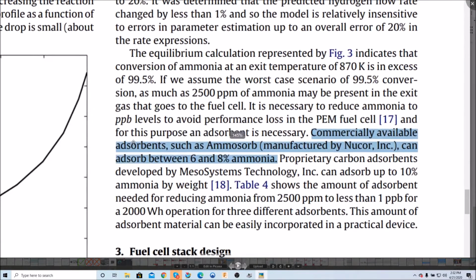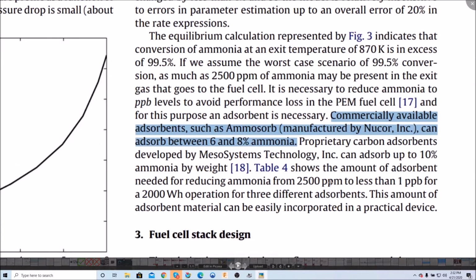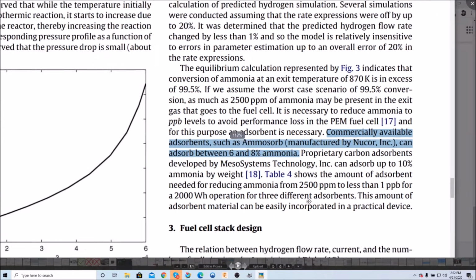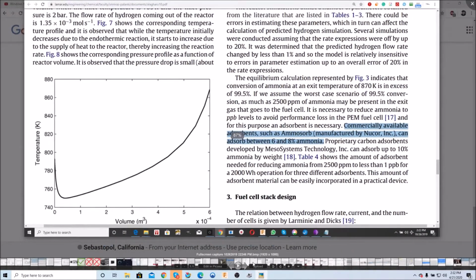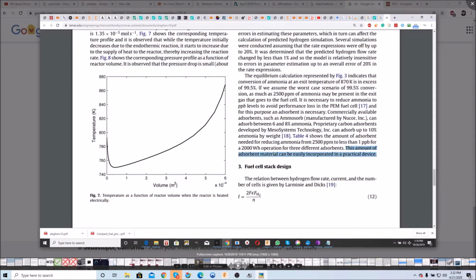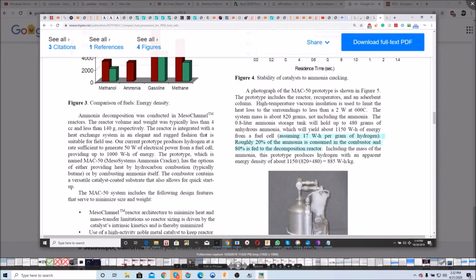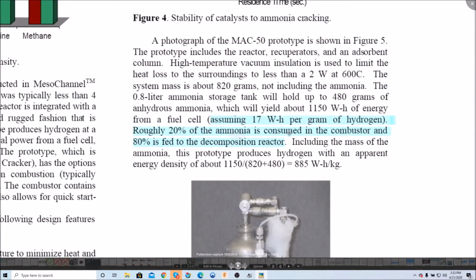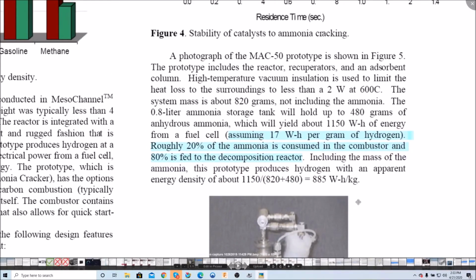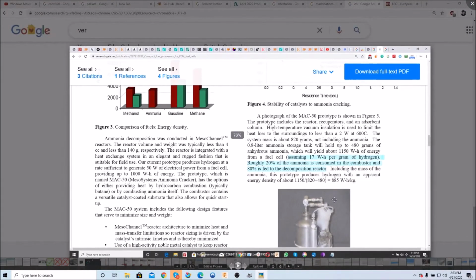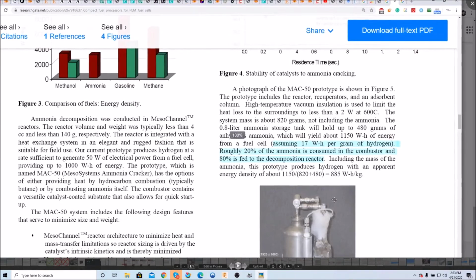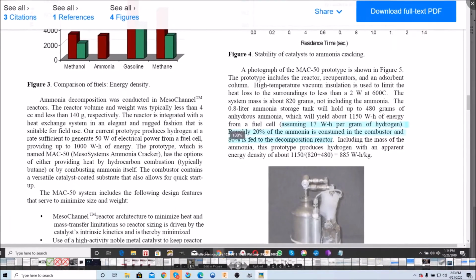So Ammosorb, between 6 and 8% ammonia by weight, reduced from 2,500 parts per million down to 1 part per billion. Okay. So 20% of the ammonia is consumed in the combustor. So they're actually burning ammonia rather than the cracked hydrogen, or I should say, the hydrogen byproduct.